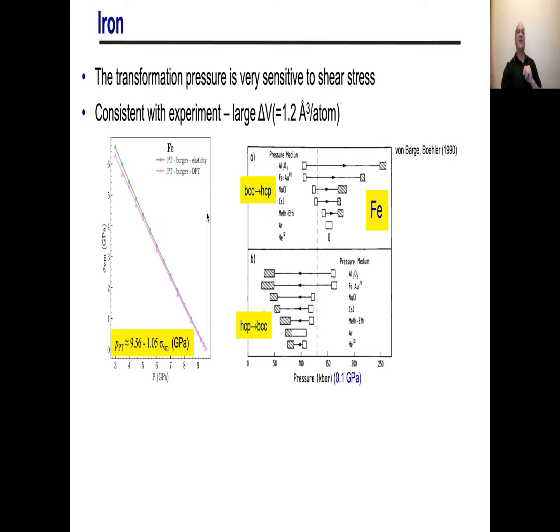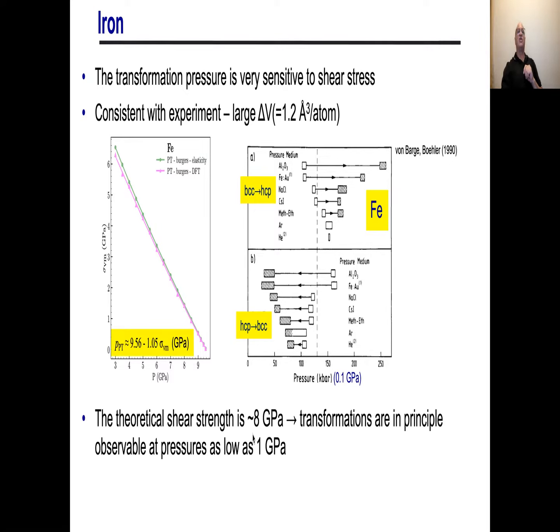Okay, so that's that. So the theoretical shear strength of this material is about 8 GPa. Sorry, that number looks wrong to me. And so in principle, one should be able to achieve the transformation at pressures as low as 1 GPa. But it never happens. It never goes down to 1 GPa, and that's because we never see yield strengths up as high as the theoretical shear strength.